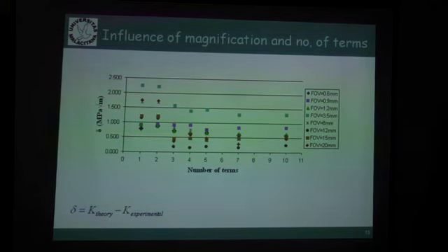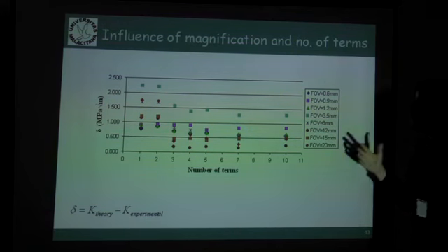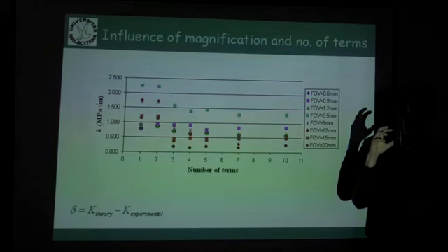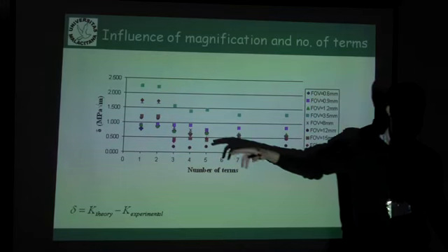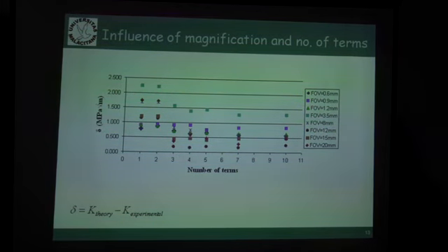And we can also see that by having a larger field of view, the resolution is actually better. So if we not only take a singular term, but all the additional terms, the resolution for evaluating the stress intensity factor improves.